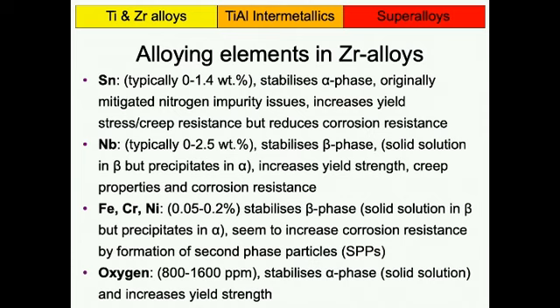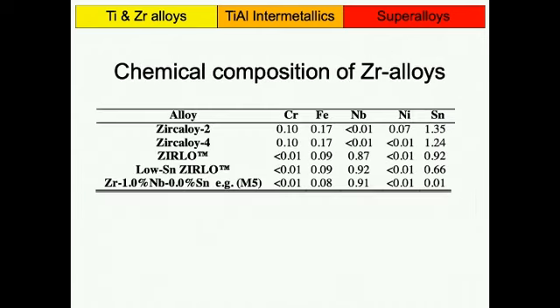We've already discussed oxygen content of titanium, and here again it's an alpha stabilizer in titanium. It's solid solution, but interstitial, not substitutional, because it's a very small element, and increases the yield strength. And what one could add here, it reduces the ductility of the material. But you find the balance. And again, having zirconium without any oxygen is practically impossible. So you have some amount of oxygen in here. And you try to balance in terms of getting enough strength without reducing too much of the ductility of the material. So that's the principle.